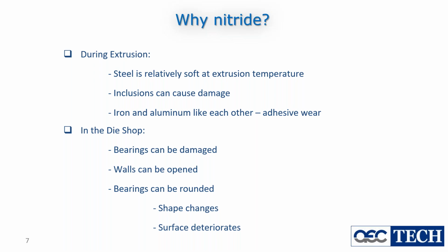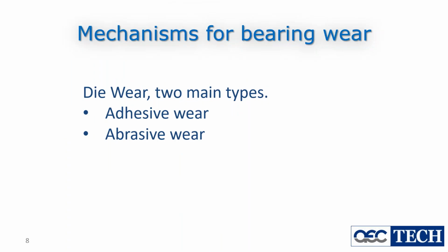If we nitride, we put this protective hard layer on the surface of the steel. And that protective hard layer means that the steel is a little bit harder, at least the bit on the end of the bearing which is nitrided. Inclusions will do less damage to it because it's hardened. Iron and aluminum, when there's a nitrided layer in there, actually don't have the same affinity, so there's less adhesive wear. It also means that when you're polishing the die in the die shop, the bearing is more resistant to your polishing. So it's a good thing all around.